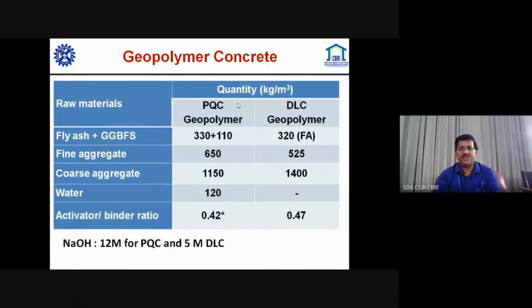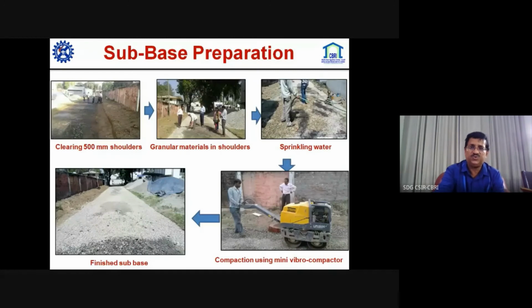Here we can use DLC with fly ash only, because we don't need very high strength. But if you want, you can use 10% of GGBS. And in PQC we have used 330 kg of fly ash and 110 kg of GGBS. Fine aggregate was 650 kg, coarse aggregate was about 1150 kg, water was 120. The activator to binder ratio was kept at 0.42 in PQC.